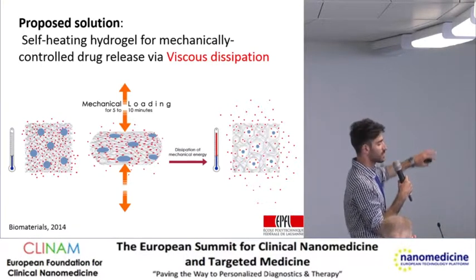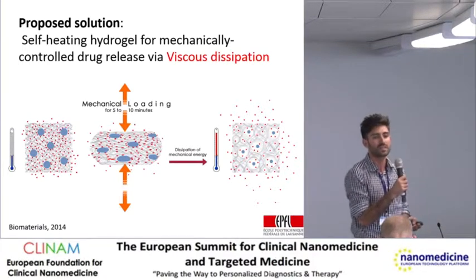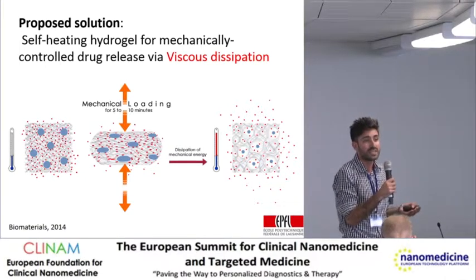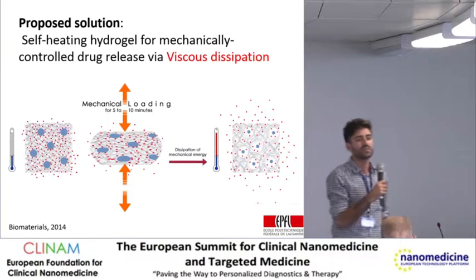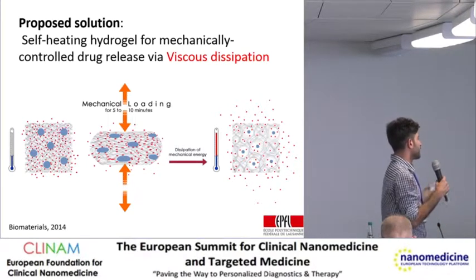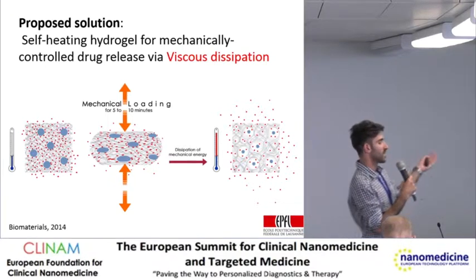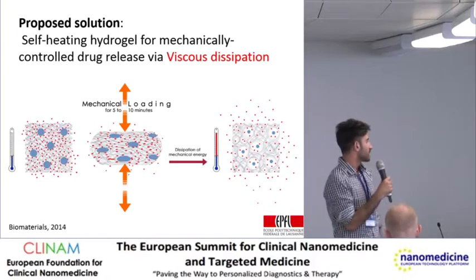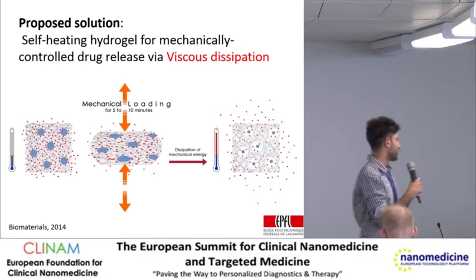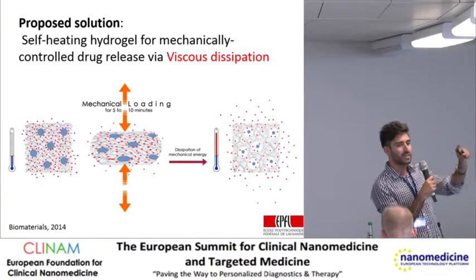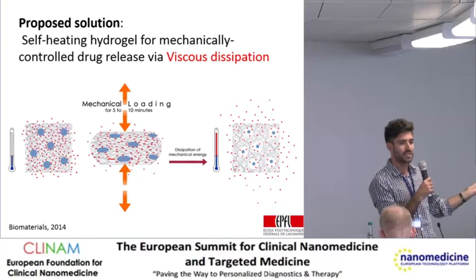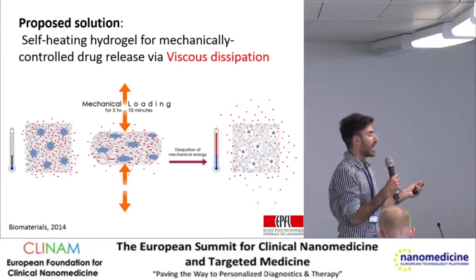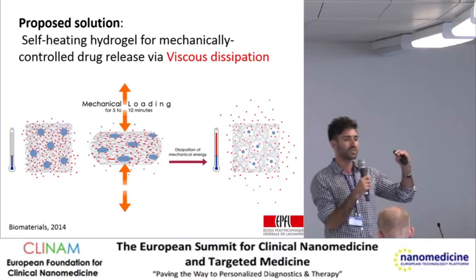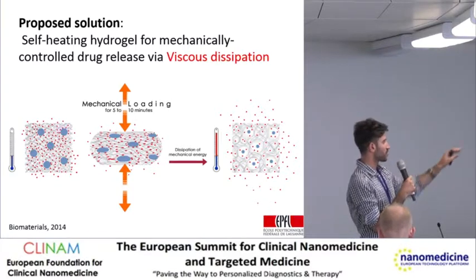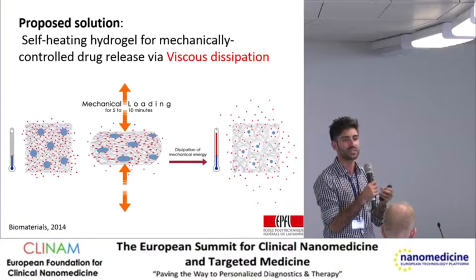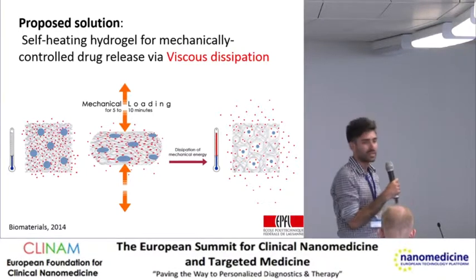When you apply load, as I said, the hydrogel is very viscoelastic. So when you apply load on a viscoelastic material, it dissipates part of the energy, which is heat, actually. And if you continue cyclic loading for specific times, by playing with the viscoelastic properties of this material, you can regulate this time to be from several minutes to half an hour, for example, what I need. At each loading cycle, the material heats up a bit. That's why we call this material self-heating, because it dissipates lots of energy. And after a certain number of cycles, the temperature reaches the temperature that we need for the nanoparticles. At this point, the nanoparticles shrink, and when they shrink, they occupy less space and increase the permeability of the gel. And consequently, you have much more drug release.